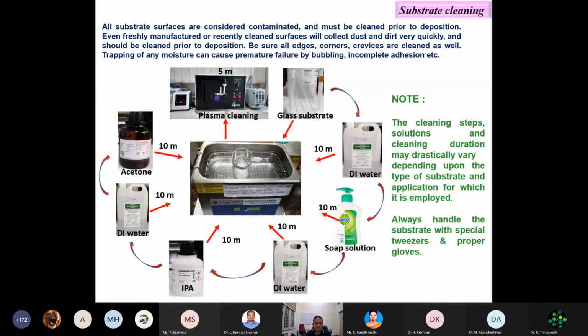And then coming to the cleaning process, how to clean the substrate. So first of all, you should decide what is a substrate, whether it is a glass or whether it is a polymer. Okay, so if it is a polymeric material, if I use strong acids, the substrate will be dissolved out. Okay, that should not happen. Or if I have a glass substrate, once again, I should not use a very corrosive substance. If I use a very corrosive substance, the surface will be etched out, and then the growth of the film may not happen properly. So the substrate cleaning is not universal.